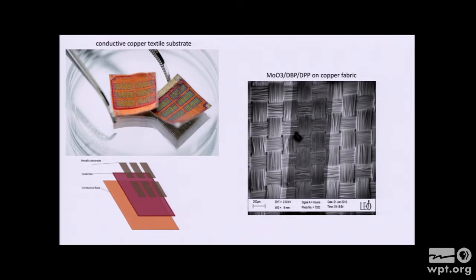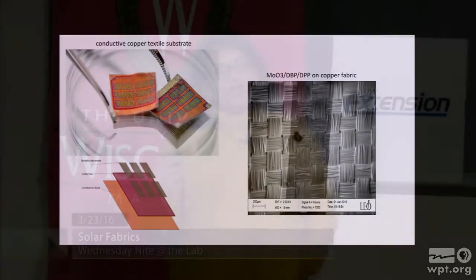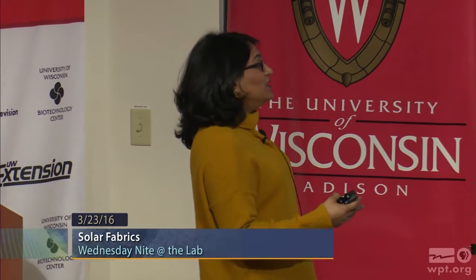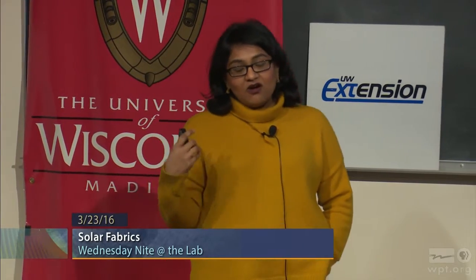And what I really want to focus on in the SEM is, again, you don't really see a lot of difference between the uncoated versus the coated fabric. You don't really see a lot of crystal clustering, even at this 200 micron scale image here. You don't see a lot of non-uniform coverage that kind of jumps out to you in the eye. And what this image is telling you is basically that these organic photoactive molecules that we're using are able to, again, coat a very, very rough fabric substrate without any breakage. All right, so we can actually use these dyes as we wish on a fabric substrate.